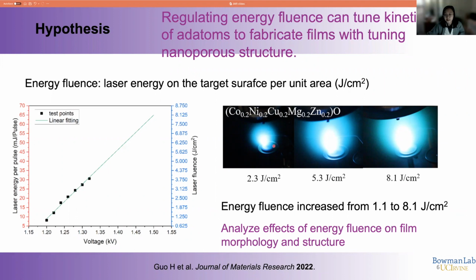When the laser hits the target surface, it will produce the plasma plume. So different energy fluence will produce different kinds of plume. The low energy fluence will produce a plasma plume with small volume. However, a very large energy fluence can produce a plasma plume with very high and brighter volume. It's because the energy fluence will change the kinetic energy of atoms.